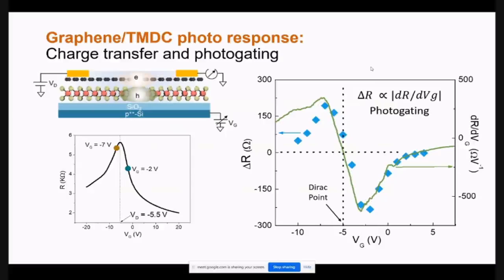Okay, but what's the physics? Let's go to the physics. So the physics essentially is what you call photo charge transfer and photo gating. That means when the electron goes from the bottom layer to the upper layer, it essentially goes into the sink because it is kept at zero potential, but the hole which is left behind acts as an additional gating agent. So it gates the graphene underneath, like positively. As a result, you see the gate effect is maximum where the R versus VG transfer characteristic is the steepest, at this point and at this point. That is where the change in resistance is maximum. And the change in resistance due to shining of light is proportional to the derivative of the resistance with respect to gate voltage. So this is what we call the photo gating effect.